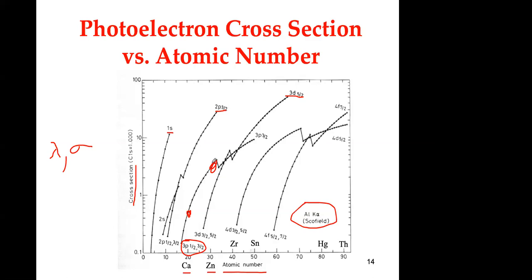So when you see in a spectrum that a peak is higher than for another element, that doesn't mean that you have more concentration. You have to be very careful. It's misleading. Cross-section might be a factor, and obviously lambda, depending on the kinetic energy that you're analyzing, as I mentioned. If it's higher kinetic energy, you will have more signal because you're looking deeper into your sample. If the energy is lower, then the depth of analysis is smaller. So those are two parameters that you need to have an idea about.